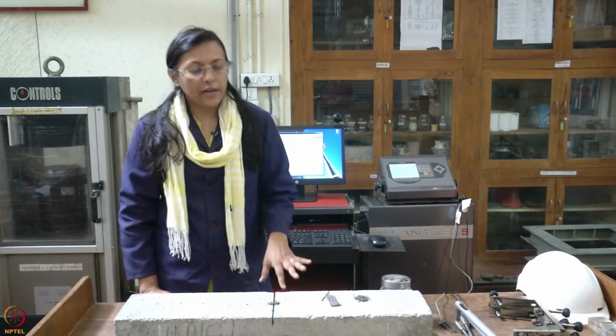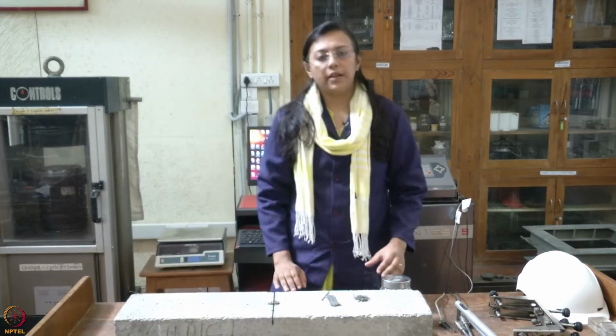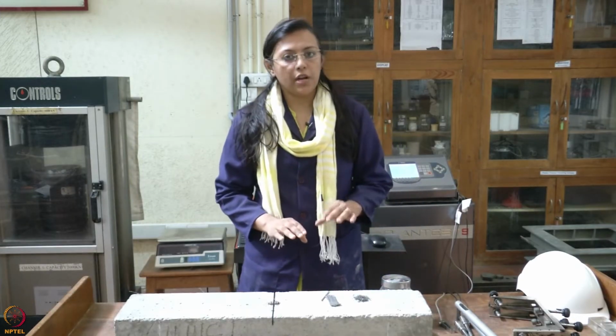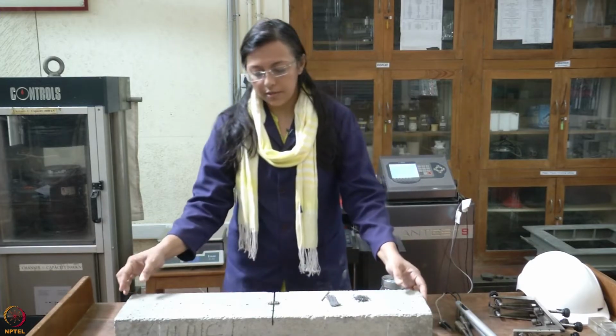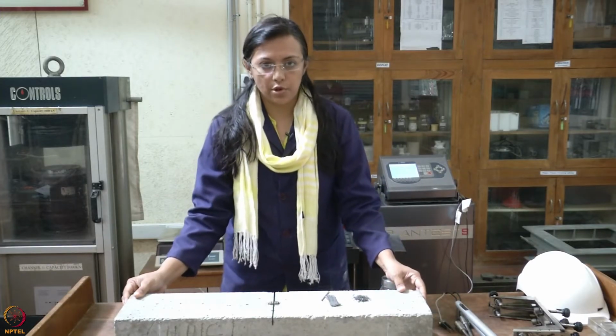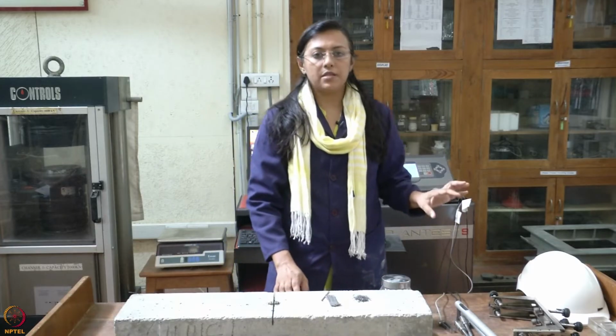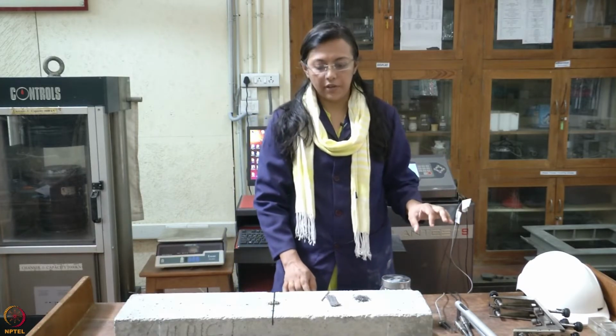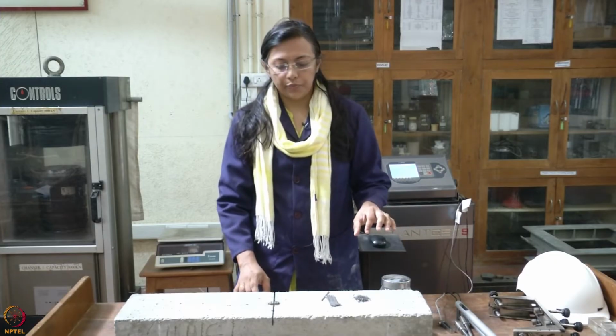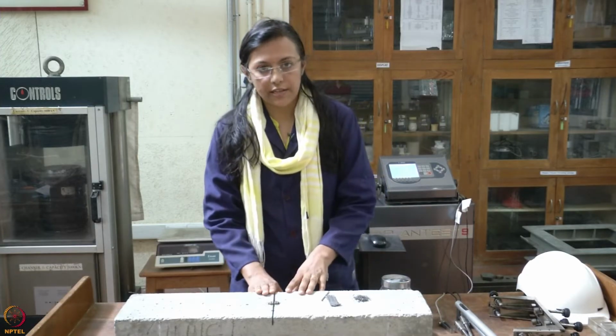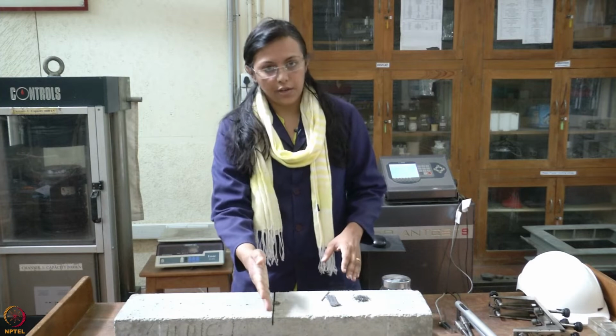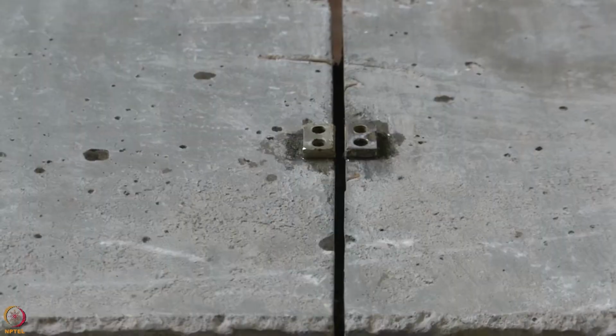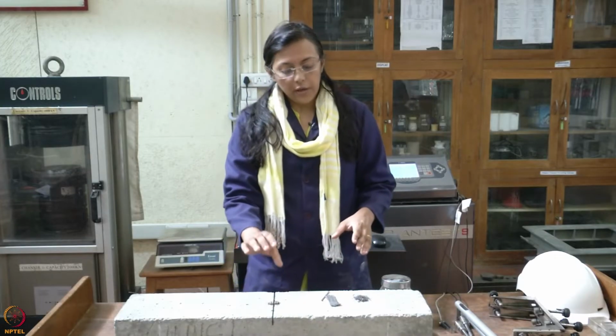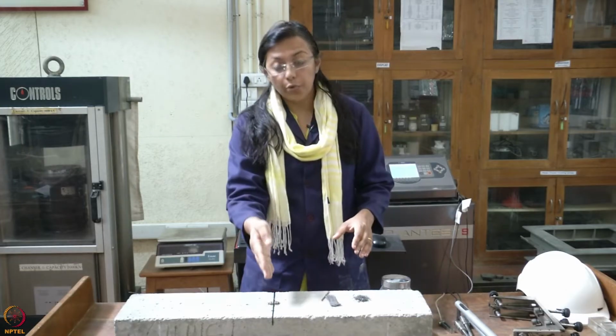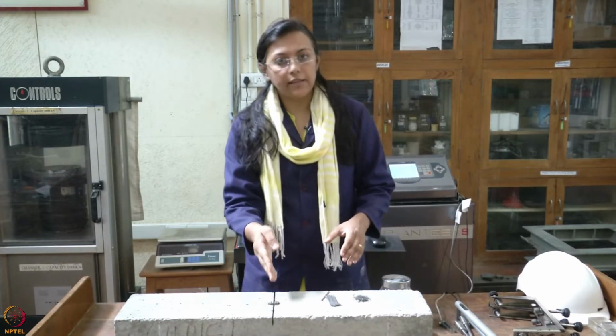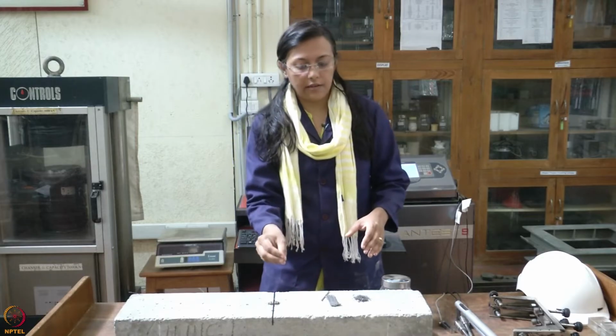Regarding the characterization of fiber reinforced concrete, there are two typical tests, the notched and unnotched beam test. This is a specimen cast of fiber reinforced concrete. This testing is based on EN 14651 and RILEM TC 162. In this notch test, we are cutting a notch in the mid width of the test specimen. Why do we need to cut the notch? We're forcing a weak plane in that area so that the crack happens there.